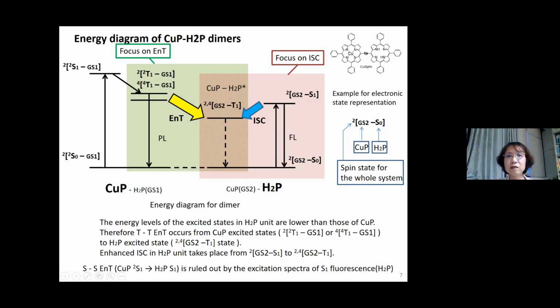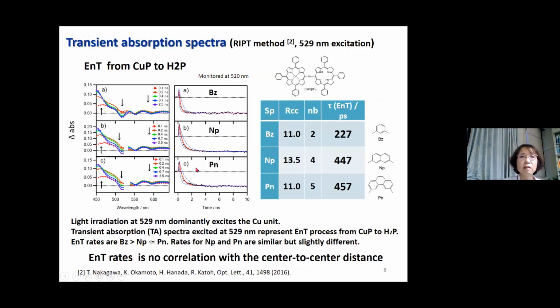Then we investigate energy transfer from the copper porphyrin to the free base porphyrin. However, direct singlet energy transfer from the copper porphyrin to the free base is ruled out by the excitation spectra of the fluorescence of free base porphyrin. So this is the result of transient absorption spectra in which we excite the copper porphyrin dominantly. If we use 529 nanometers, we observe transient absorption spectra in which the free base triplet is generated from the copper porphyrin triplet.